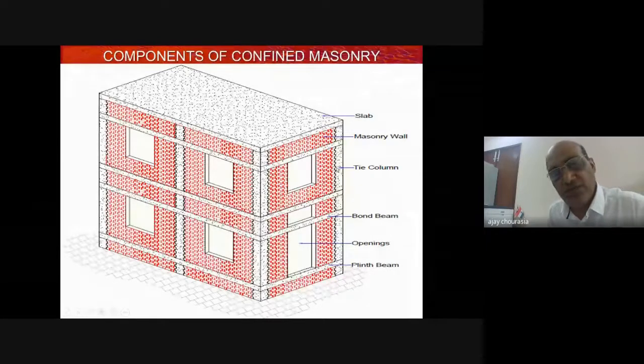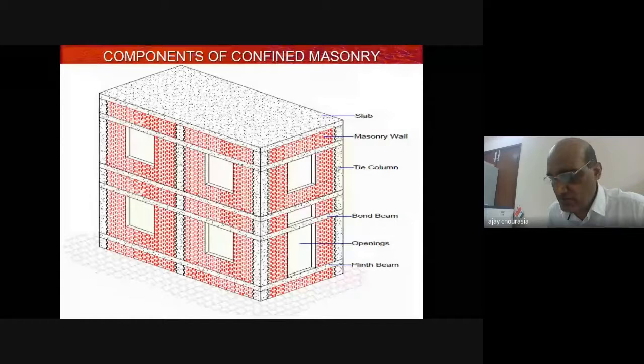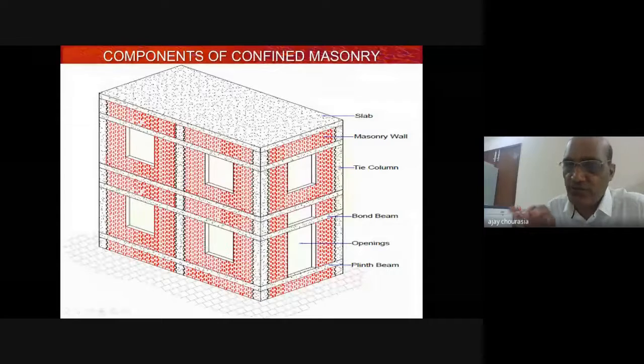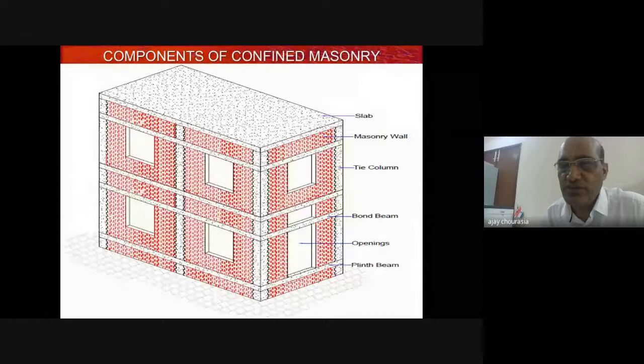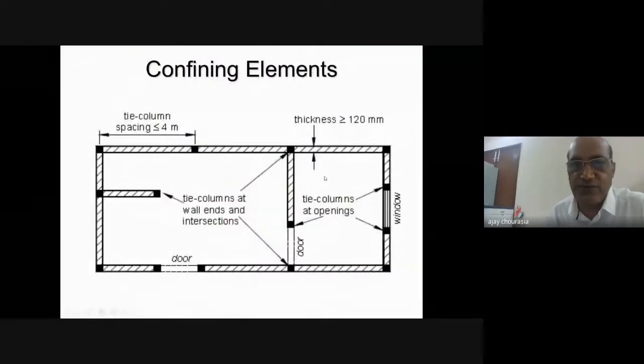Unknowingly, in the practice that is being followed, people are providing almost half a brick. As a result, it is very difficult to pour and compact the concrete, and honeycombing takes place. So it is good practice that we should give this toothing in the range of 25 to 30, 40 mm. That again has a certain relationship with your aggregate size. If you have a 20 mm maximum aggregate size, then it is 2T. That is basically the limiting factor.